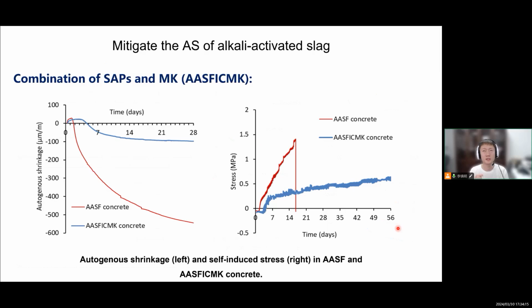So I thought, okay, internal curing can be very effective for the later age shrinkage, and metakaolin is really useful for the early age. If I combine these two, the ICA, meaning internal curing, and metakaolin, maybe it can reduce the shrinkage in the whole period. Actually, that comes true. So we can see that compared with the reference concrete, if we combine internal curing and metakaolin, the shrinkage is reduced more than 80% in the whole period.